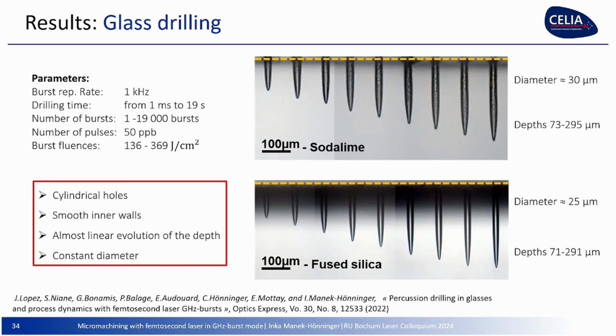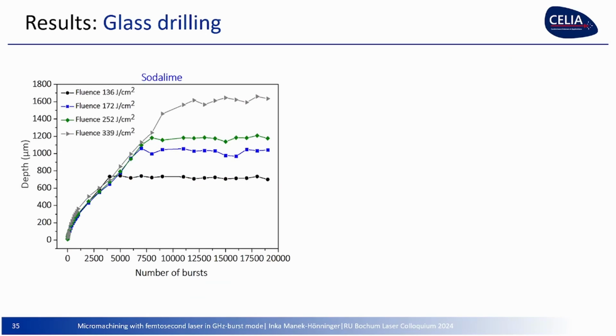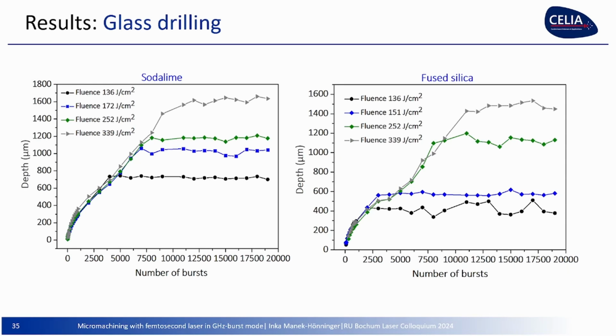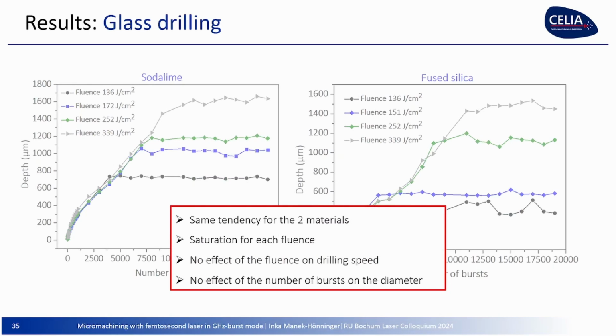So what happens if we drill for longer times? We drill up to 19 or 20 seconds, and we have for soda lime these curves. And this is increasing fluence, more and more fluence. What will it give in fused silica? It gives the same thing, the same trend. If you look at the scale, the depths are not exactly the same. We have the drilling depth as a function of the number of bursts. You see that's the same here. The same tendency for these two materials. You always have a saturation at each fluence, which gives the final depth of the hole that can be reached. There's no influence of the drilling speed.